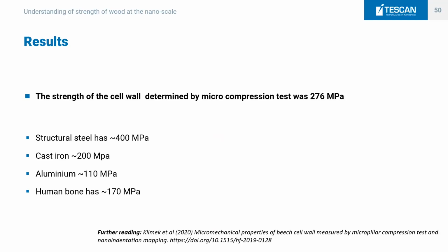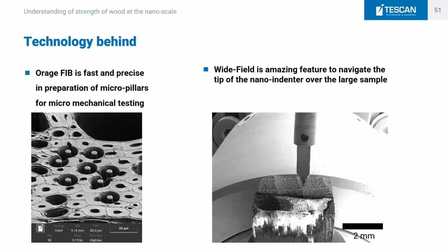So what was the technology behind here? Well, we use the focused ion beam, and we integrated the nanoindenter inside of the chamber, and we could do all of these experiments on our materials. So it just gives you an idea that it's not just about the focused ion beam, but it's also about setting up experiments, and you can modify the system according to the researcher's needs.